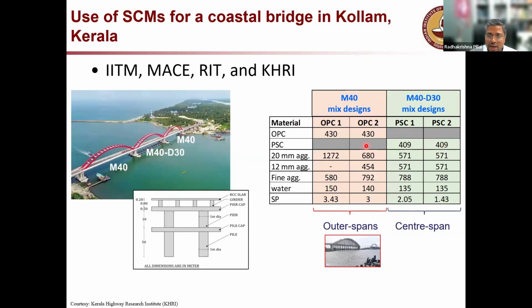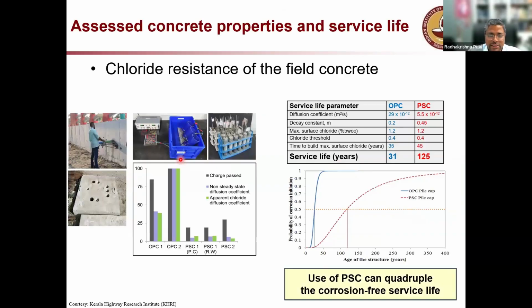So we tried 4 mix designs and proved that the slag concrete with D30, that is 30 is the minimum resistivity for that concrete. So we proved that it is possible. We did a lot of testing on the field, on the actual bridge elements. We took cores from the bridge element. This is actually the approach road for the bridge. We took samples from the field cast concrete, and what we found is when you go for slag concrete, you are able to get 125 years as the service life. Whereas in the OPC concrete, it was coming to be 31 years.